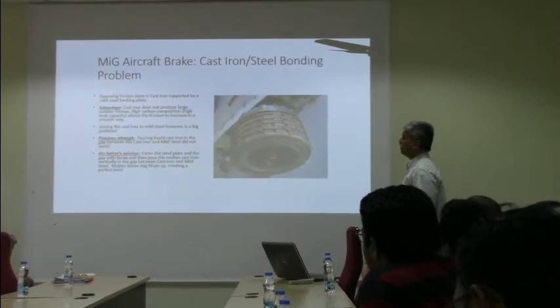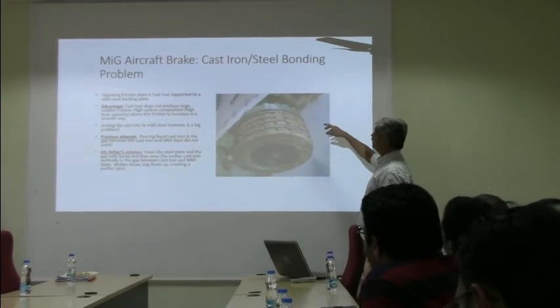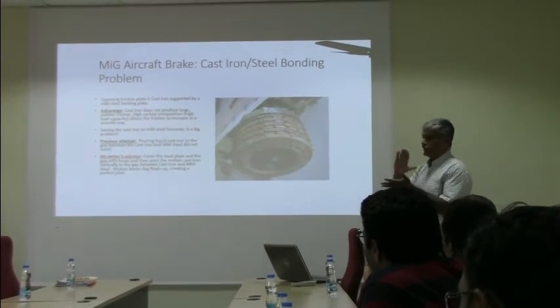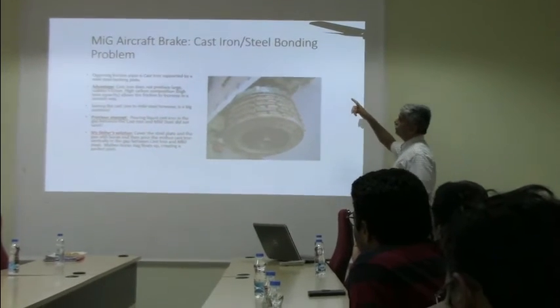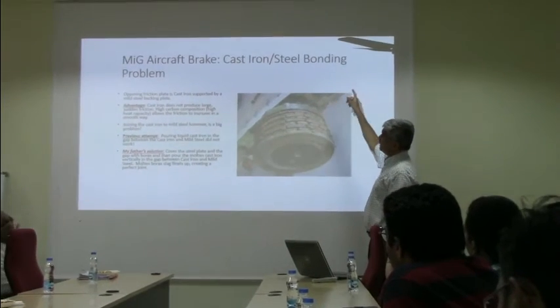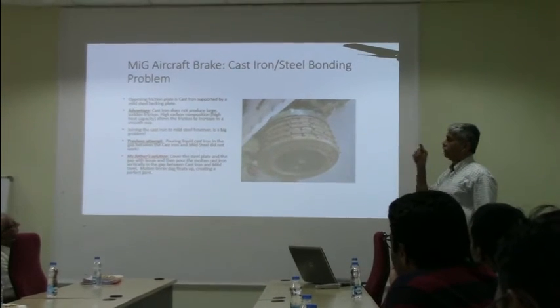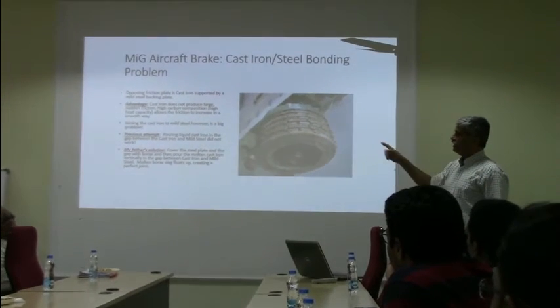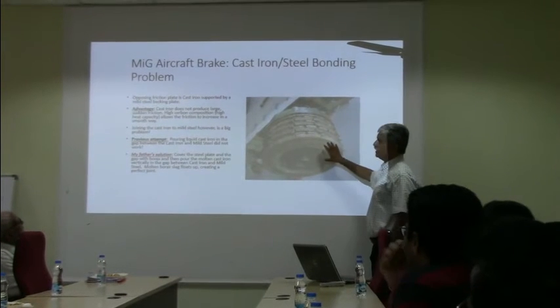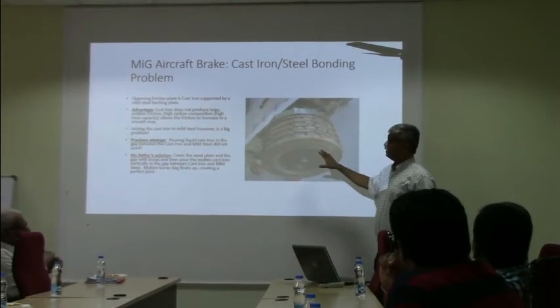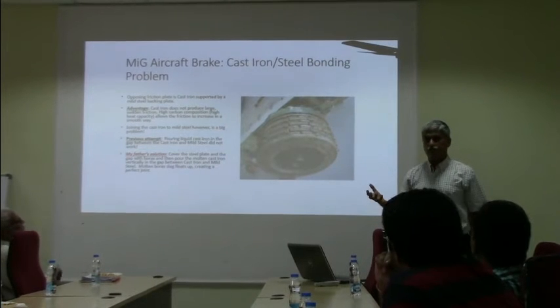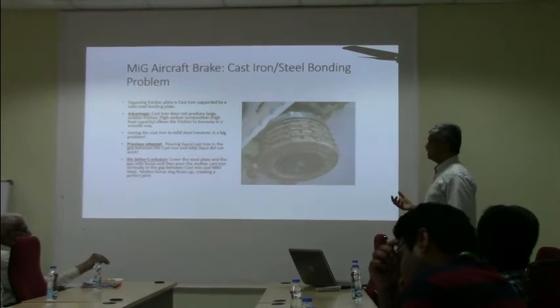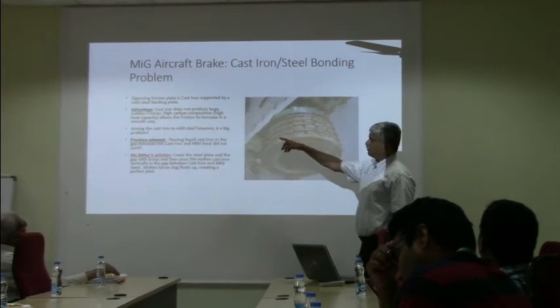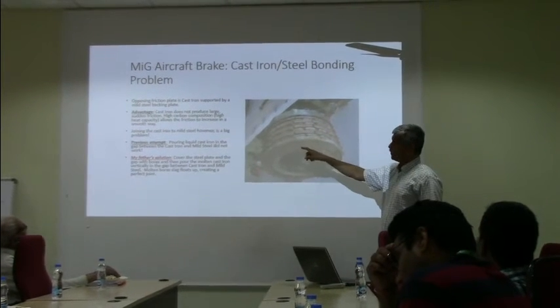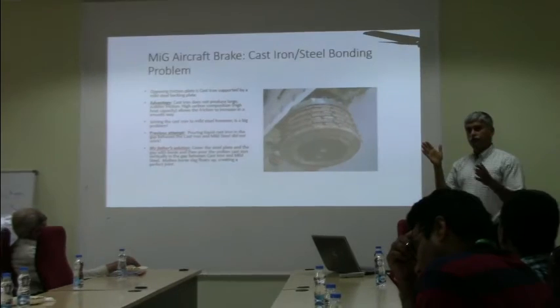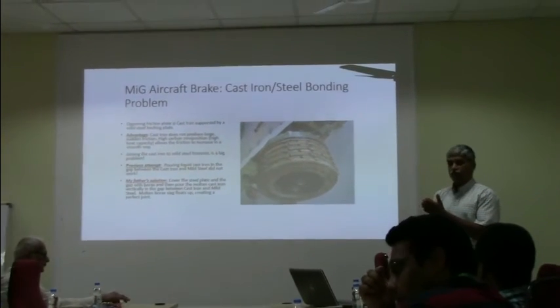So the second technical problem was how do you attach the other mating surface, which was cast iron. Attaching the cast iron to steel again was a huge problem. The reason cast iron is very advantageous is because cast iron has a high graphite content and therefore high heat capacity. So it can absorb a lot of heat as opposed to, say, mild steel. And so it allows the friction to increase in a smooth way. But welding the cast iron to steel is not an easy job, right?